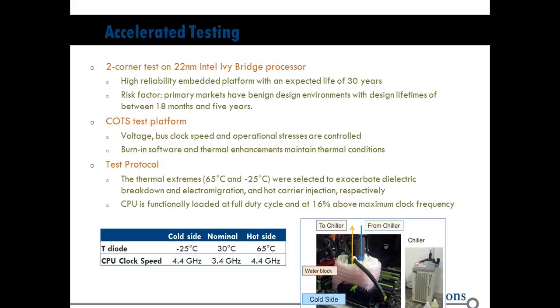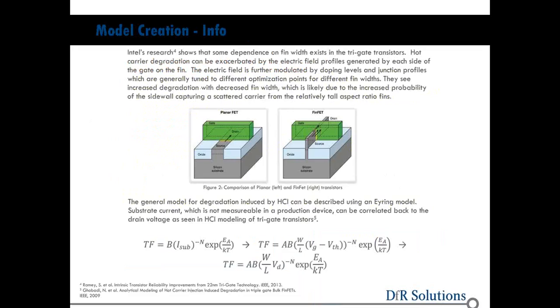Okay, so we went ahead and ran these, and the goal was to run them for about 9 months and see what we could actually uncover. It's worth noting for the model creation on this that through a lot of papers that we were able to find, there were no new failure mechanisms introduced, and the classic models for, say, dielectric breakdown or hot carrier effects, which exist for the planar transistors, actually also take place in these FinFET designs.